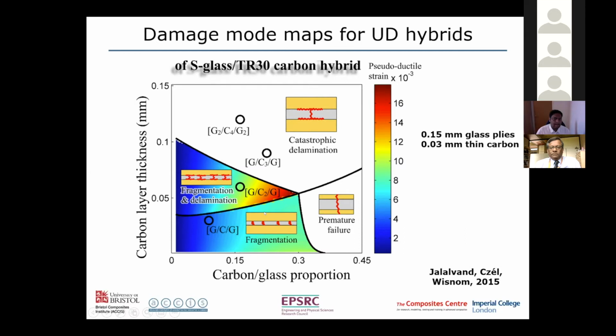And the colors represent the amount of pseudo-ductile strain. So if we're in this region here, close to this transition, we can get 1 to 2% of pseudo-ductile strain, additional strain over and above the strain in the carbon. Of course, we don't want to be too close to this, otherwise we risk going over into the catastrophic failure modes. So we want to be in this region, not too close.